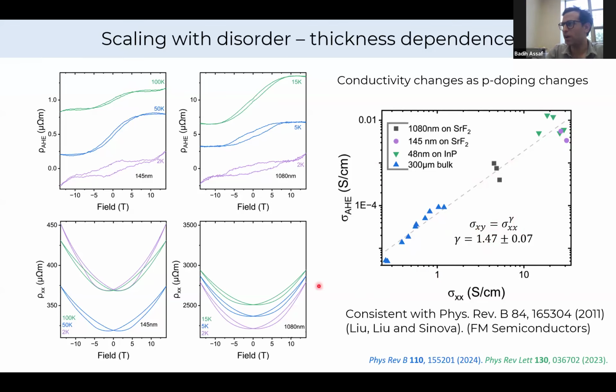This is consistent with the hopping regime for the anomalous Hall effect, which was actually studied pretty well in magnetic semiconductors in the past. It makes sense in this case for it to be in this regime simply because manganese telluride is a semiconductor with quite a low carrier density, giving a relatively low sigma xx, a relatively low longitudinal conductivity. So this is not a surprising finding, but it hadn't been observed to this point, so it's important to highlight it. But what's more important is that these films on strontium fluoride fall on the same line as bulk.